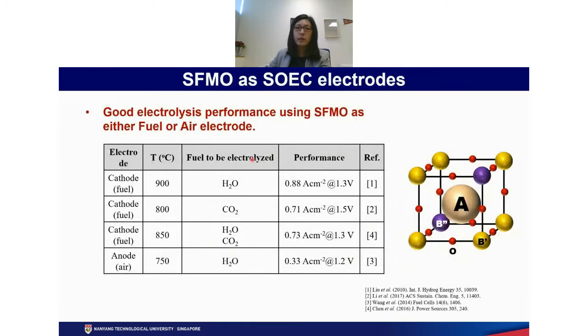Okay, so there is some work that has studied SFMO in the SOEC, either as a fuel or air electrode. So in this table, we find three are working on a fuel electrode, and one is on the air electrode, at about 700 to 900 degrees centigrade. And there is fuel in terms of water, CO2, or co-electrolysis. And the performance is quite decent. So this gives people some confidence that SFMO is indeed promising as a SOC electrode.